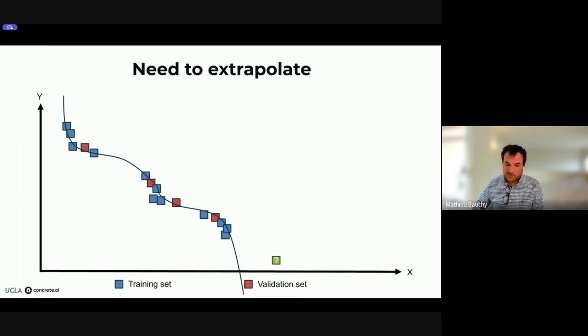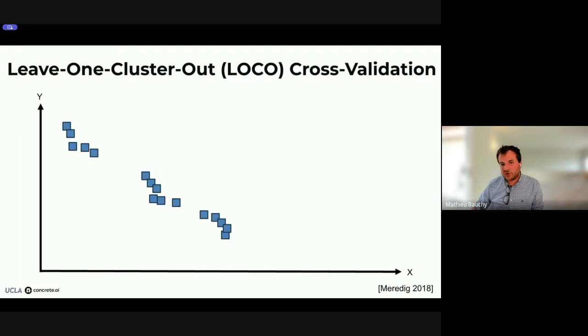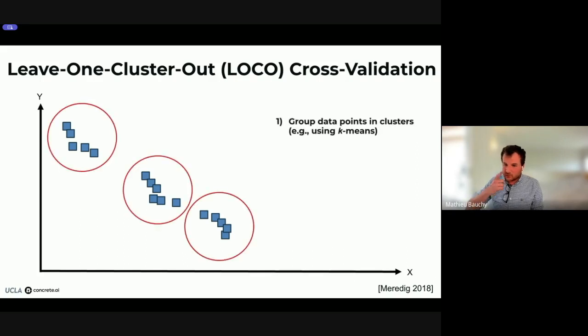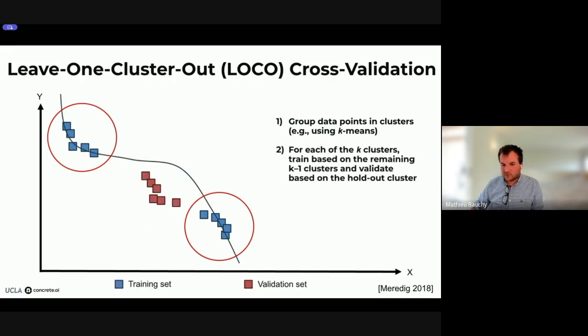And for this, we need to favor models that can extrapolate outside of the range of the training sets, and that can be reasonably able to generalize outside of the training sets. And so the approach that we have found to be the most efficient for that is to leave one cluster out, or LOCO cross-validation. And the idea of this is that the first thing is that we take our data sets and we group them into clusters, clusters of data points that look like each other. So we can use different approaches for that, but probably even a simple k-means algorithm would work reasonably well for that.